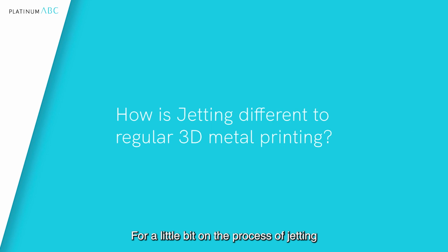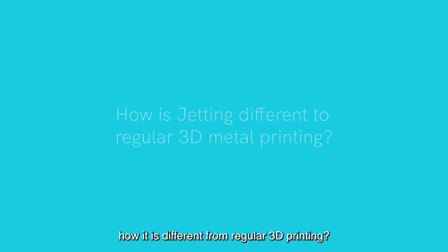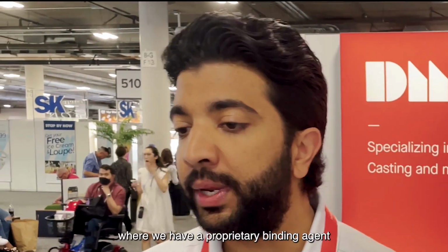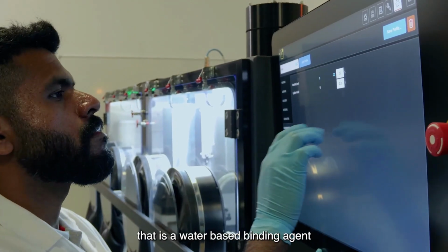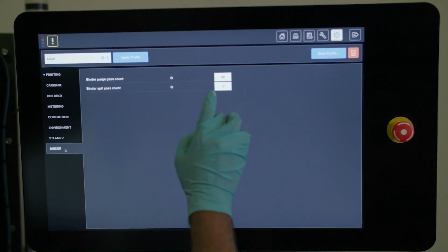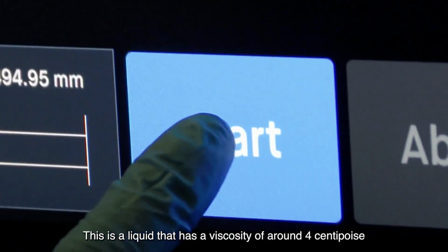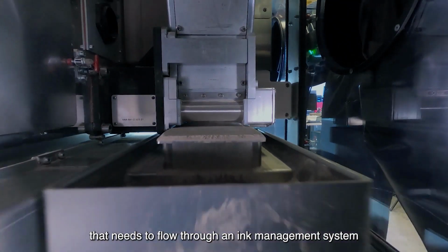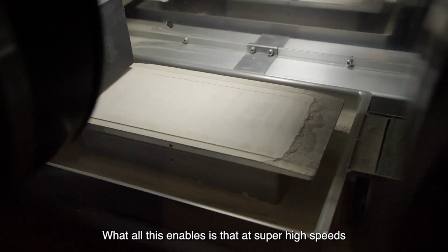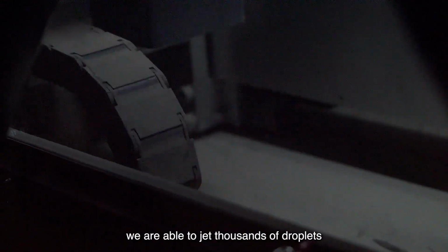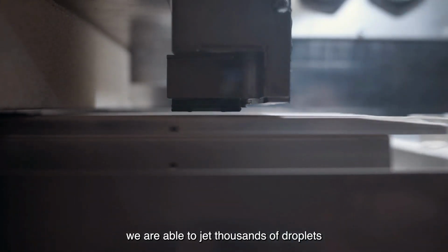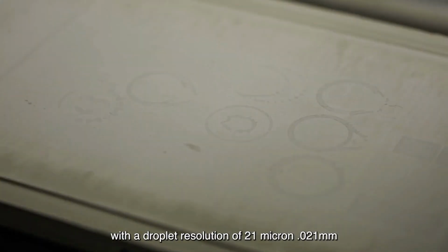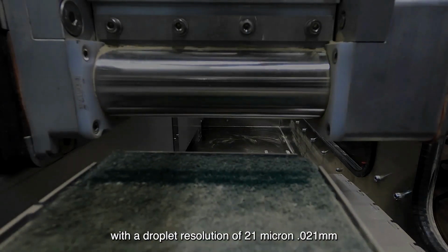For a little bit on the process of jetting, how it is different from regular 3D printing. Jetting is the process where we have a proprietary, water-based binding agent. This is a liquid that has a viscosity of around 4 centipoise that needs to flow through an ink management system in the printer. What all this enables is that at super high speeds, we are able to jet thousands of droplets onto a bed of powder with a droplet resolution of 21 micron, 0.021 millimeter.